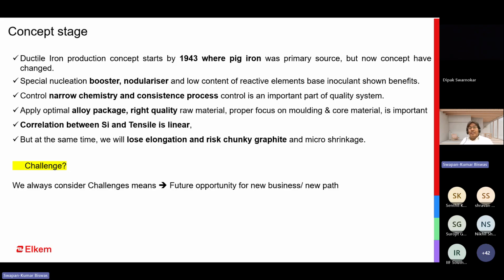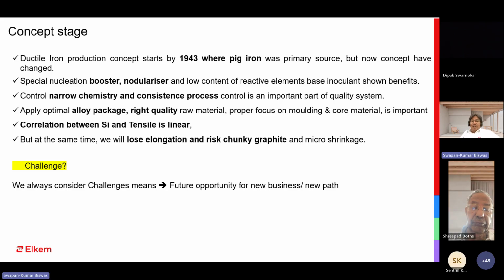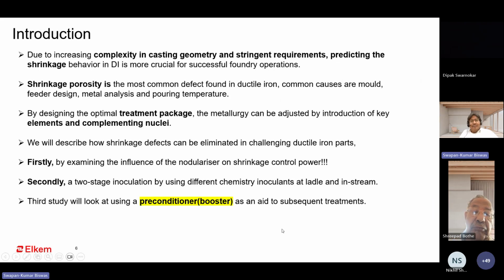So that is the raw material side, and then molding and core are also very important. Otherwise, it will be difficult, as correction on one side will not help you get consistent results. Everybody knows there is a linear relation between silicon and tensile strength, but when you increase the silicon level, there will be other problems, such as chances of chunky graphite. So you have to decide which is the best option. And when you take care of the challenges, definitely it will give a new business path and new opportunity. So we should accept the challenge and work on it. There will be a positive outcome.